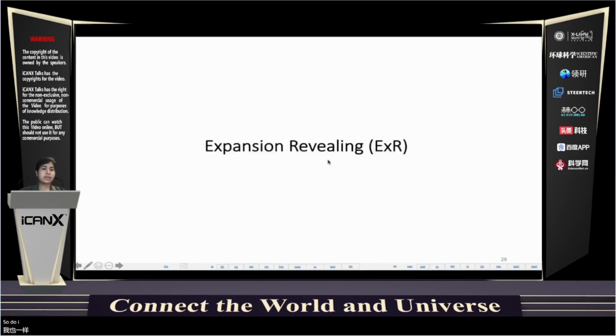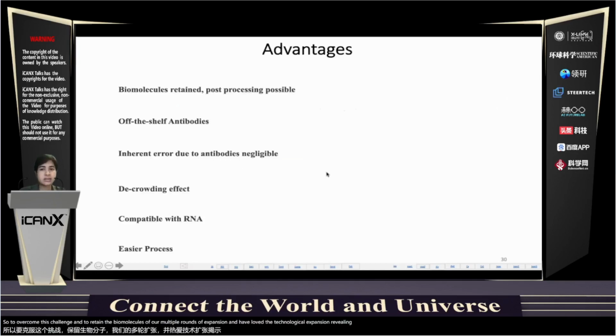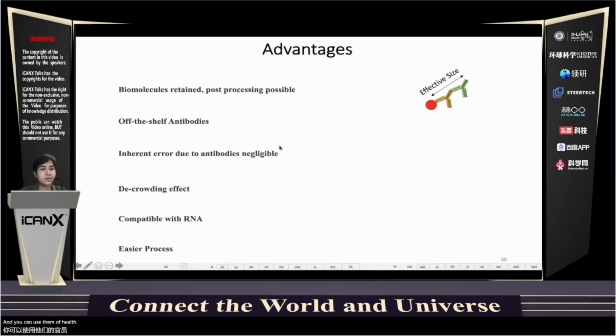So to overcome this challenge and to retain the biomolecules over multiple rounds of expansion, we developed a technology which we called expansion revealing. And the advantage is, of course, apart from the fact that you retain the biomolecules and you can use off-the-shelf antibodies to target and visualize your biomolecular nanostructures, it also has this advantage that the effective size of the antibodies that we can use in this case basically gets reduced by the expansion factor.